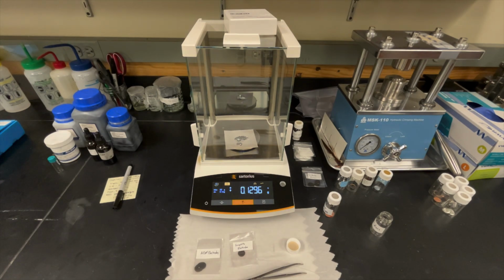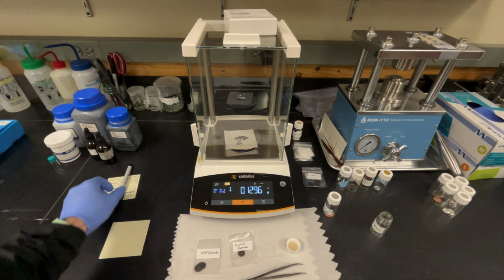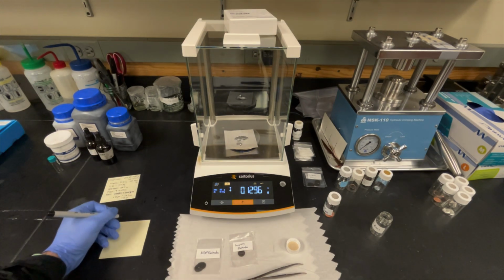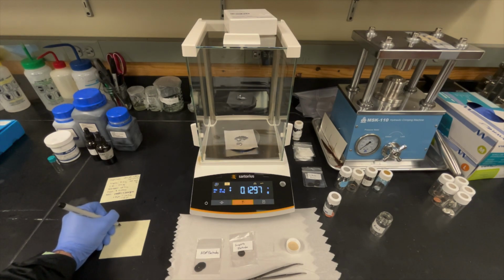However, we know that ideally the electrode contains approximately 80% active material out of the total, so we multiply the total amount by 0.8 to get the weight of the active material on the electrode. This information is important because we can use that to characterize the device.